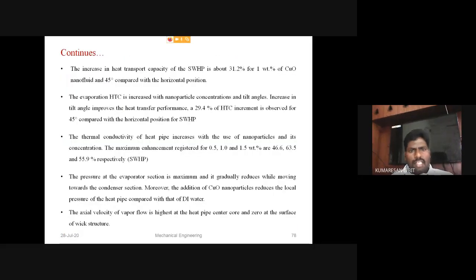Then the increase in heat transfer capacity of sintered wick heat pipe is about 31.2% for 1 weight percentage of copper oxide nanofluid and 45 degree inclination compared with that of the horizontal position. Then this HTC is increased with the nanoparticle concentration on tilt angle, and for the sintered wick heat pipe, it attained an optimum value, that is a maximum value at 45 degree inclination.